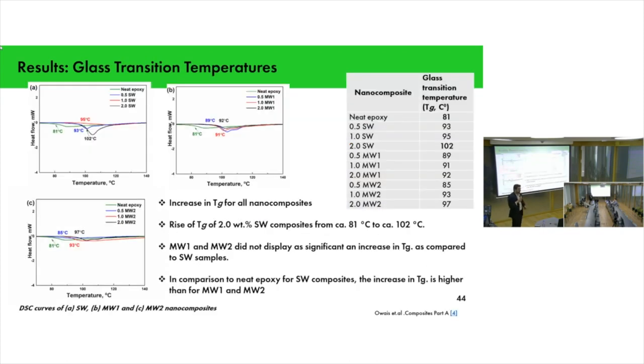So when you talk about the glass transition temperatures, we see that there is an increase in glass transition temperature for almost all composites, but specifically there is a significant increase in glass transition temperature from neat epoxy to 2 weight percent single wall, at 102°C, which is not significant in the other multi-wall carbon nanotube based composite systems.